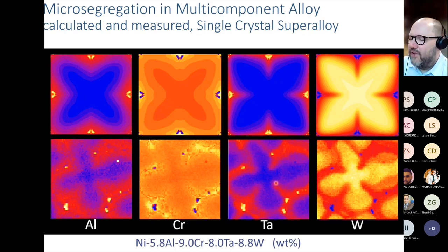So we find that aluminium and tantalum show very similar segregation patterns. The element enriches in the liquid and depletes within the solid. But in aluminium, the segregation profile is spread out a bit further. Aluminium diffuses within the solid phase about an order of magnitude faster than tantalum, so we have a lot more diffusion going on during the solidification stage. We see then the gamma prime forming in between the dendrite arms as well, but we're not forming an awful lot of gamma prime. It's about 1% or so. And all of that agrees quite well with the measured segregation patterns. The position and the concentration of the gamma prime is correct, the segregation pattern is correct, and the smeared-out segregation profile and the difference between aluminium and tantalum we find.